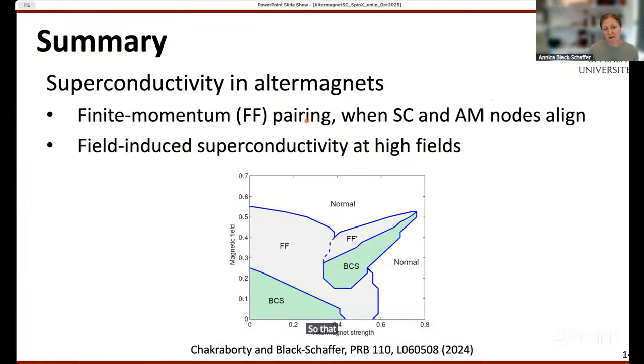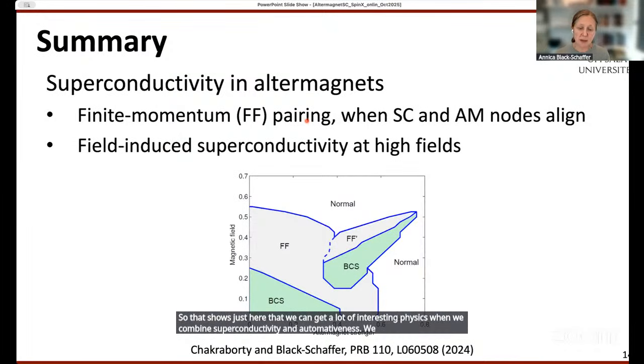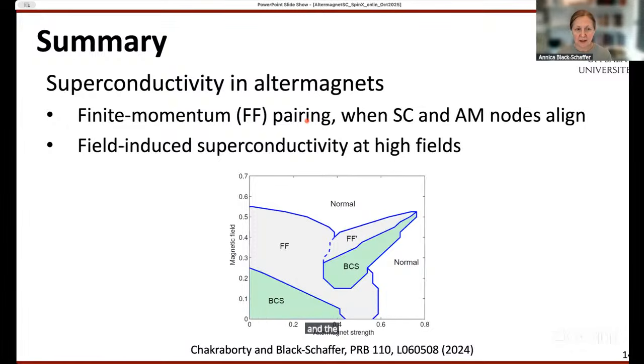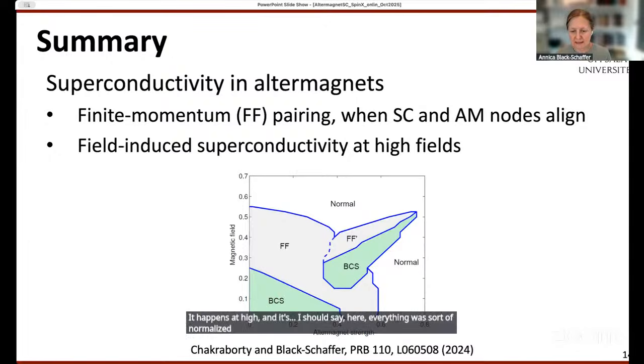So that shows that we can get a lot of interesting physics when we combine superconductivity and altermagnets. We get this finite momentum pairing. This is very hard to find, especially if you turn off the magnetic field. It exists in conventional superconductors in a magnetic field, and it happens when the superconductor and the altermagnet nodes align, and then there is this field-induced state, which I would say is even more unusual to find. That happens at high fields, and I should say here everything was renormalized and nice as we theorists often do, but we could do some estimate of how big this field is, and these would be quite big fields, but probably measurable. It's not beyond what we can produce.